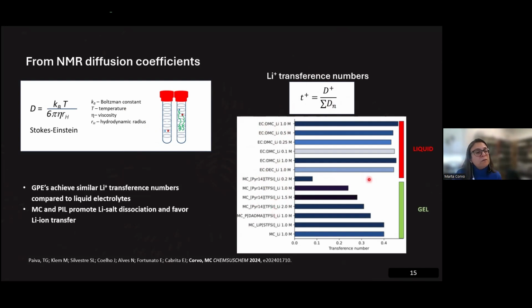What we are looking at here is, of course, the liquid electrolytes have higher transference numbers. That is expectable. But what we were happy to see was that with our gel polymer electrolytes, these ones here, we could change the transference numbers. We got different transference numbers according to the different compositions and different structures of the polyionic liquids that you see here. Most interesting for us is that it's possible to enhance these lithium transference numbers by changing the identity of the polyionic liquid, of the matrix that you are actually using.